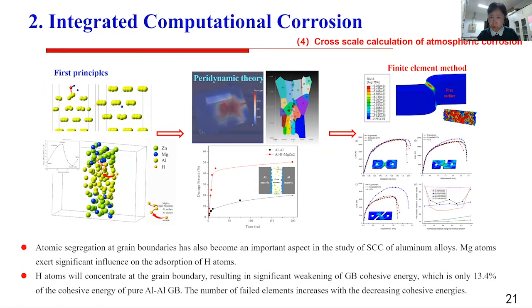The fourth part is about the cross-scale calculation of atmospheric corrosion. We use first principles to get the hydrogen and atom diffusion and absorption behaviors, and then input the parameters into the peridynamic theory. After that, we use the transfer parameters, the cohesive interface and the grain boundary energy as the transition film parameters, input to the finite element method to get the cross-scale calculation.